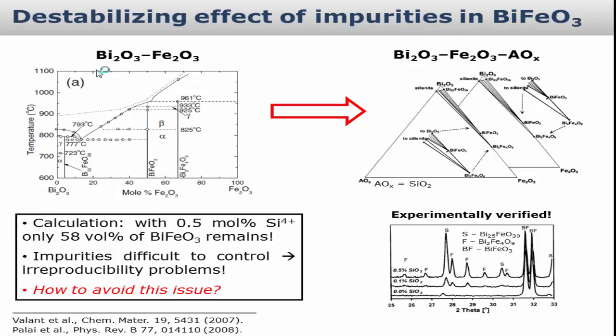Basically, you're switching from a binary phase diagram, which is what you want to have, but in reality you should have, let's say, an impurity. That's the case of silicon oxide. We have a ternary phase diagram, and the silicon oxide will be incorporated into the bismuth-rich phase. So it will form its own bismuth-rich phase, the sillenite one, which will have a certain solid solubility with the iron one, and this is how the tie line goes, as shown here. Basically, you get a very tiny and very stretched triangle in the phase diagram. It's very stretched, which means that when you're with a composition here with a bit of silica inside this triangle, you will basically have all three phases: this one, the sillenite and the bismuth ferrite, in thermodynamic equilibrium at that temperature.